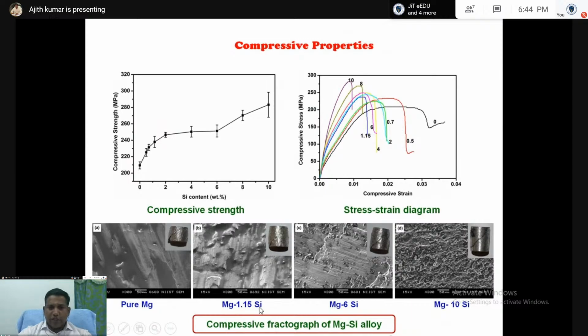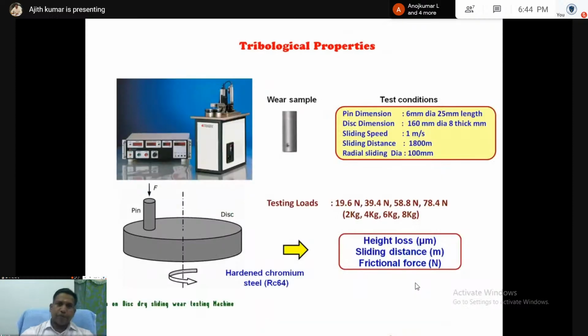When you add Mg-1.15 Si, the minimum small shear bands are there. In Mg-10 Si, because of more primary Mg2Si, the shear bands are more. So it is immediately breaking, but it is showing more compressive property. Then we can go for tensile property,